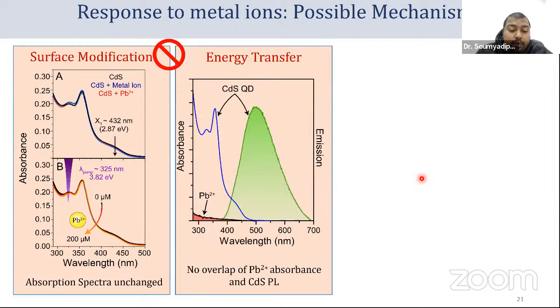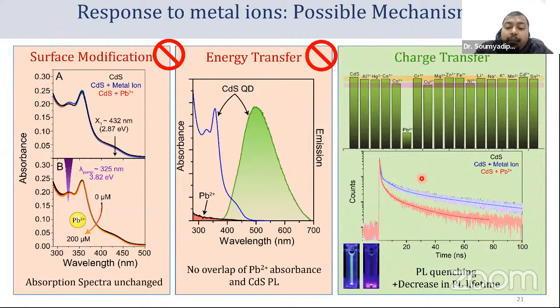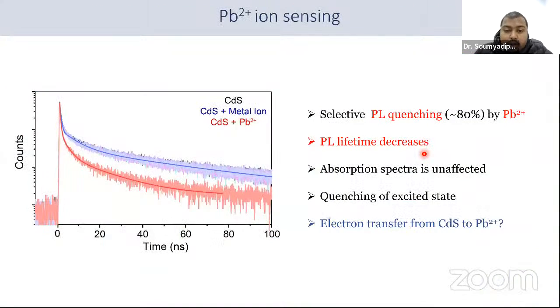Now, if we get the absorption spectra of lead 2+, you can see there is no overlap between the lead 2+ absorbance and the cadmium sulfide PL, so there is no possibility of energy transfer. But in presence of lead 2+, the lifetime decreased rapidly, and you can see the photoluminescence is totally quenched. This is an indication of charge transfer.